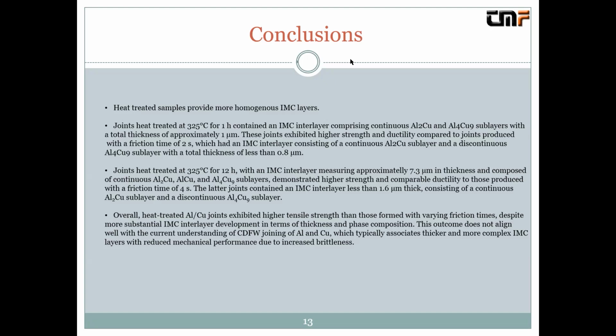Joints made by heat treatment at 325 degrees for 12 hours showed intermetallic layers 7.3 micrometers thick, composed of those 3 sublayers, and demonstrated higher strength and comparable ductility to those made with a friction time of 4 seconds. That intermetallic layer was 1.6 micrometers thick and consists of a continuous Al2Cu sublayer and a discontinuous Al4Cu9 sublayer. So overall, heat-treated aluminum copper joints exhibited high tensile strength, and those strengths were higher than those formed by varying the friction times, despite more substantial intermetallic compound layers developed in terms of thickness and phase composition.